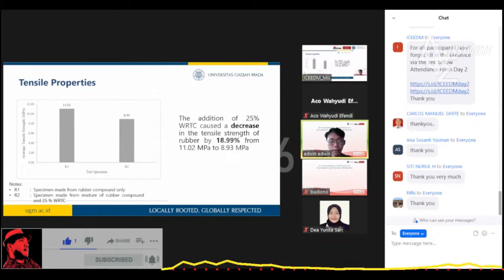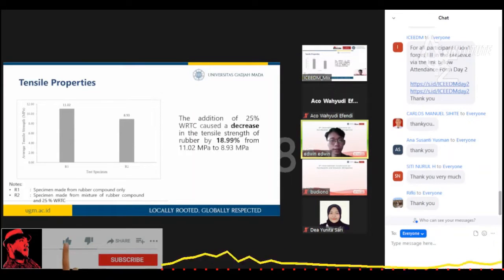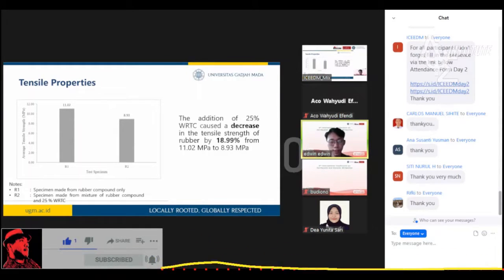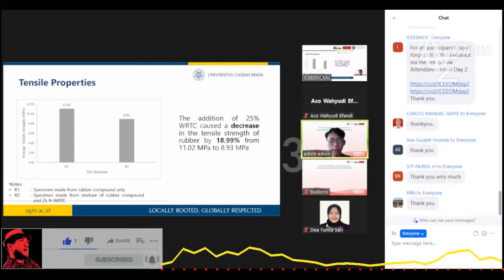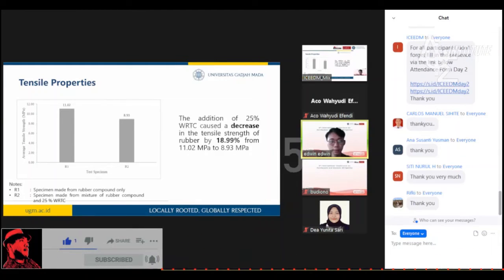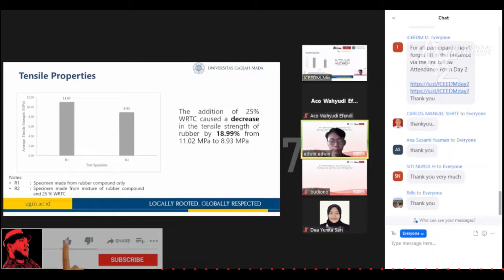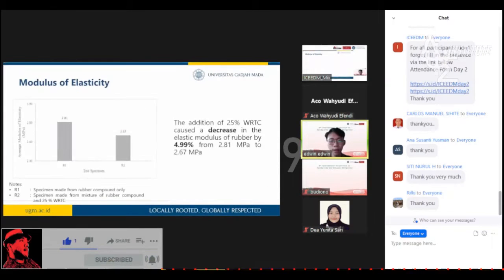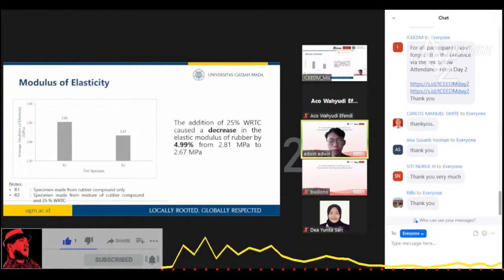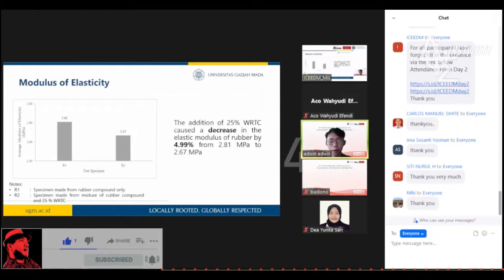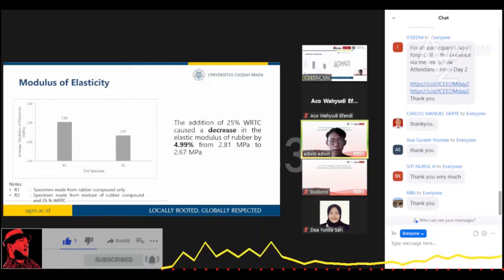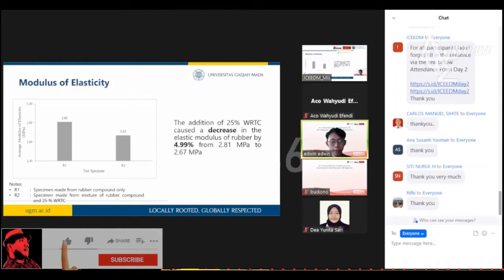Different from the hardness test results, the results in the tensile test showed that the addition of 25% WRTC caused a decrease in the tensile strength by 19%. And this is the results for modulus of elasticity of rubber, where it showed that the addition of 25% WRTC also caused a decrease in the modulus of elasticity by 5%.